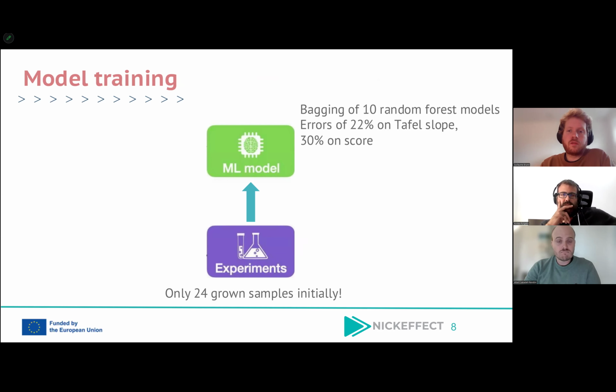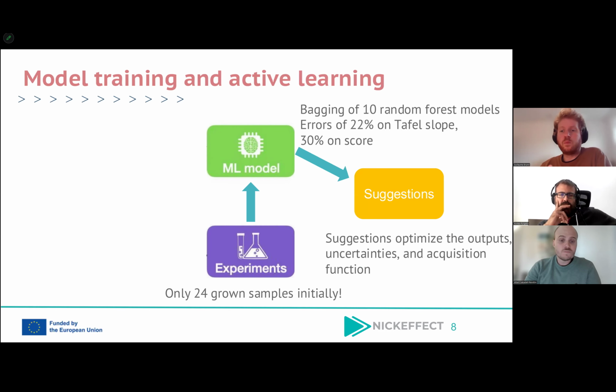And so you can see we have errors of 22% on the Tafel slope, of 30% on the score. These errors are quite large, but I mean, we have 24 samples, so that's the best that we can do at that stage. Still, we can use the machine learning model to provide suggestions of the next electrodeposition parameters to try. So these suggestions will be, for instance, the parameters where the score is the largest according to the model. So at what temperature, at what current density, and in what bath will the score be the largest